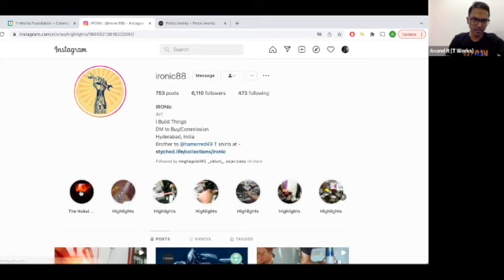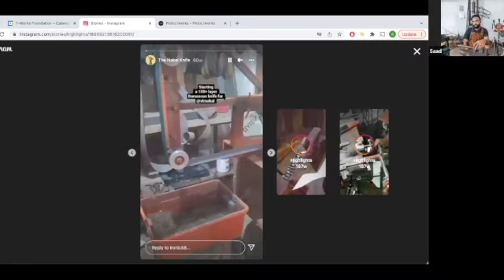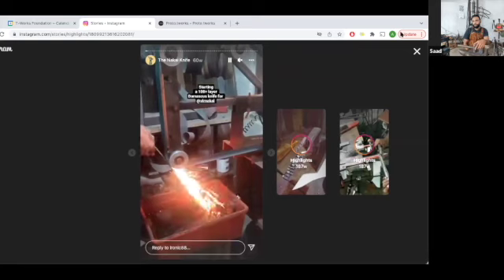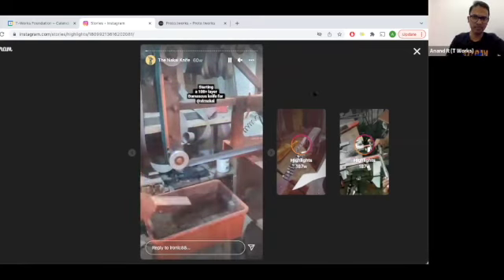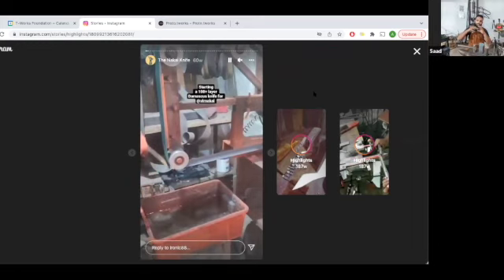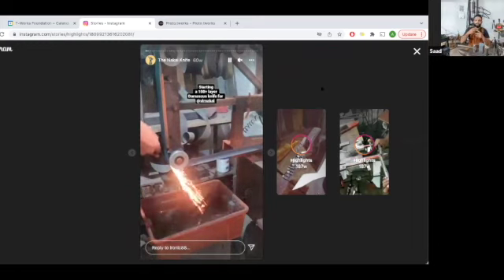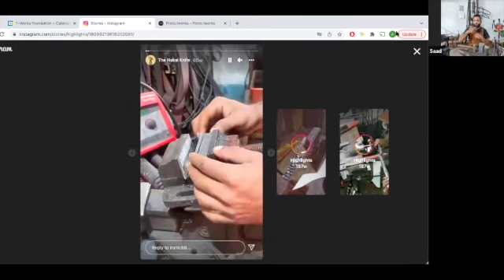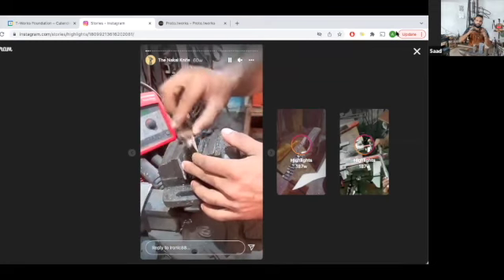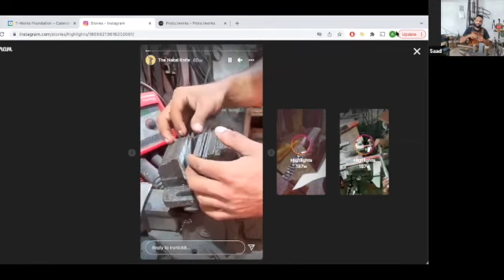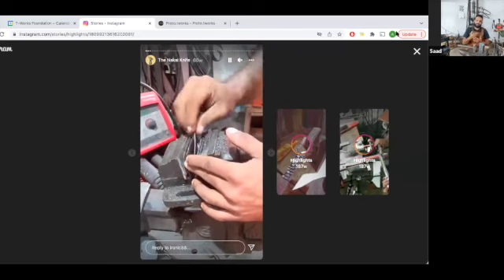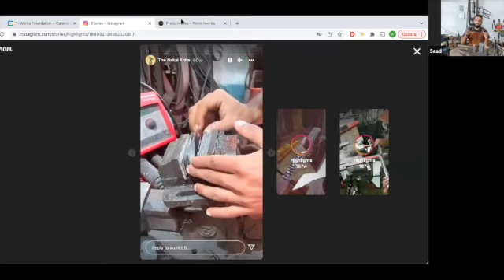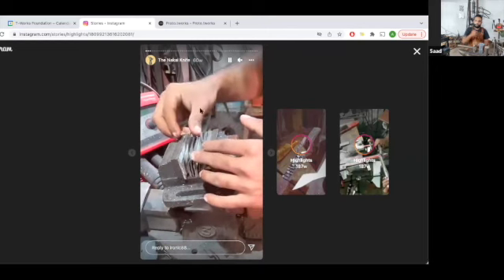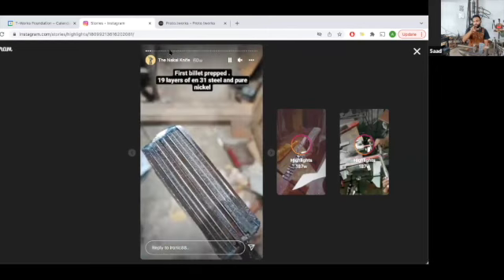Sure. So the idea about Damascus steel is that you take two different steel alloys and you layer them up, and then you forge weld them together, and you manipulate those layers to create different patterns. Once the blade is completely forged out, hardened, hand sanded and polished, when you dip it in acid, the acid reacts to the different layers differently, and it reveals the pattern within the blade. So here you can see me stacking up two different steel alloys.